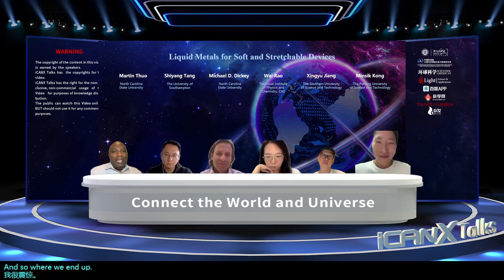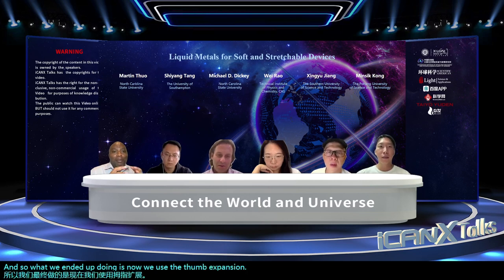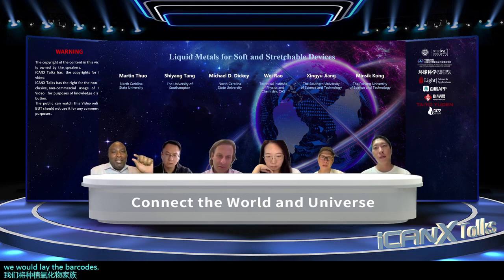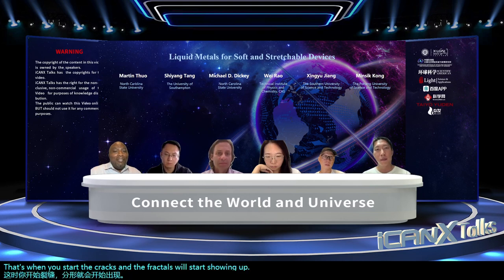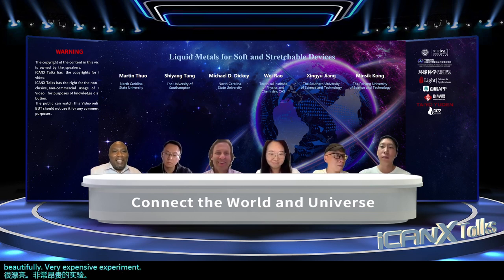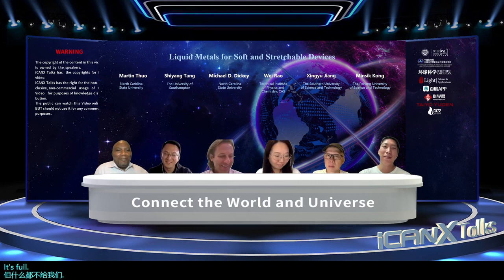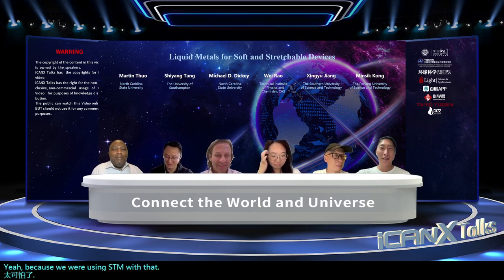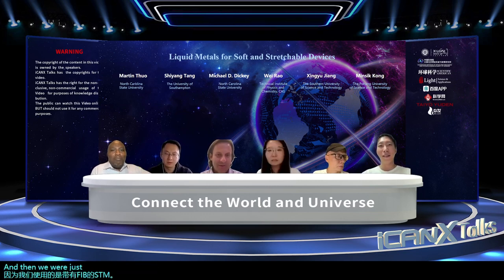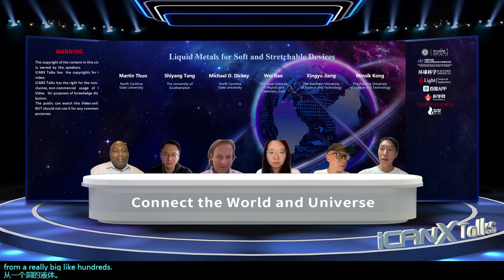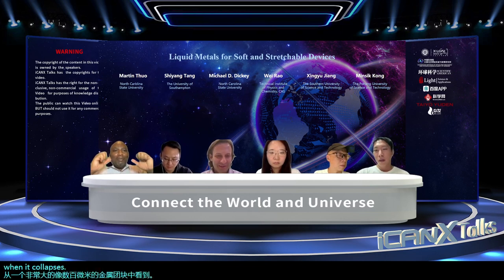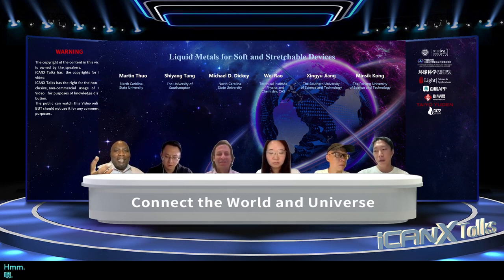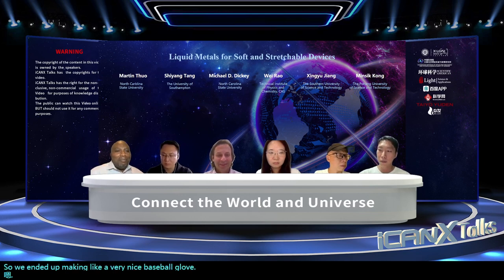And so what we ended up doing is we used thermal expansion. We'll grow the oxide thermally, and then we would let the bulk oxide, when it's hundreds of microns, that's when the cracks and the fractals would start showing up. But when you have the native oxide, we tried, we failed beautifully. Very expensive experiment, but gave us nothing. Because we were using SEM with a FIB on it, and we were just blasting the liquid from a single hole, from a really big, hundreds of micron blob of metal, to see when it collapses, what's going to happen. So we ended up making a very nice baseball glove, but not scientifically publishable.